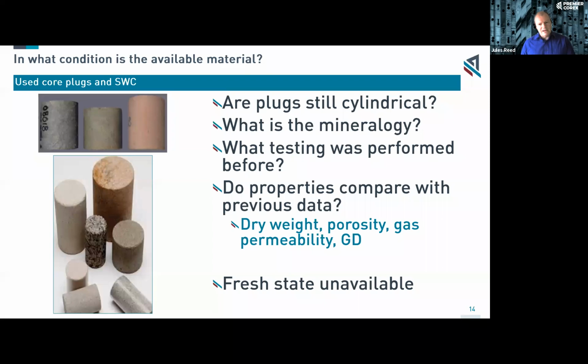We then need to consider what the impact of cleaning and resaturating with the water is. We need to make sure that we've got a good handle on our water salinity, and that it's not causing problems with those clays through the various cycles of testing. And so what we will do is a pre-study to look at that,